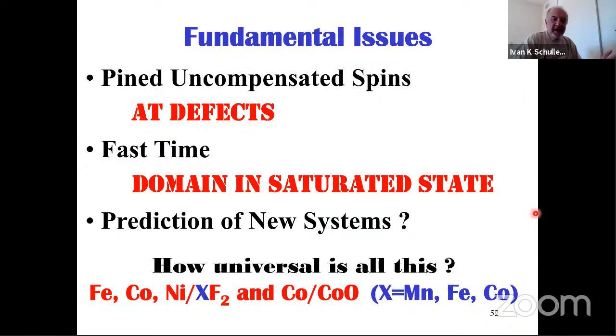And the key to this is this business of having defects in the antiferromagnet. And there are these domains in the antiferromagnet. You can see that if there is a domain in the antiferromagnet, then that's what couples one layer, like those in the three-layer system that I showed you, to another layer, because there are these domains in the antiferromagnet that matter for this new type of ferromagnetic material.